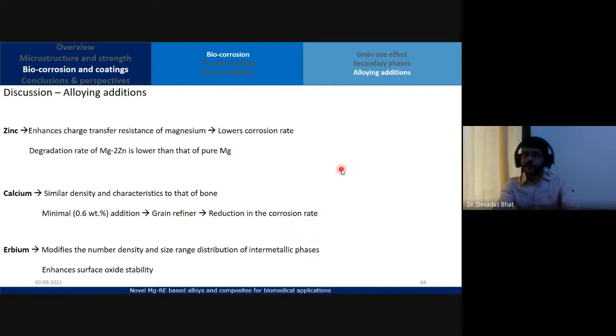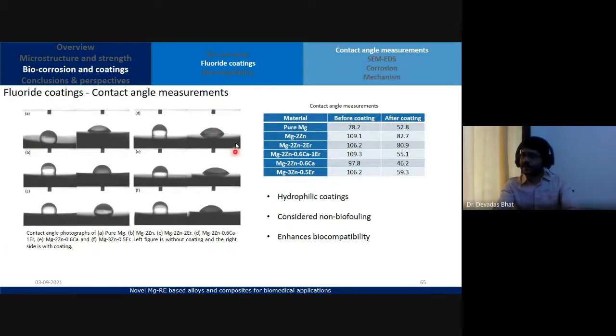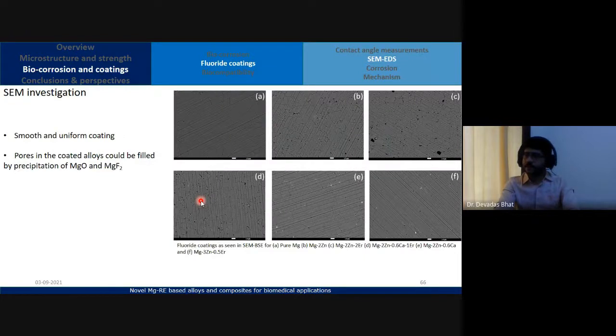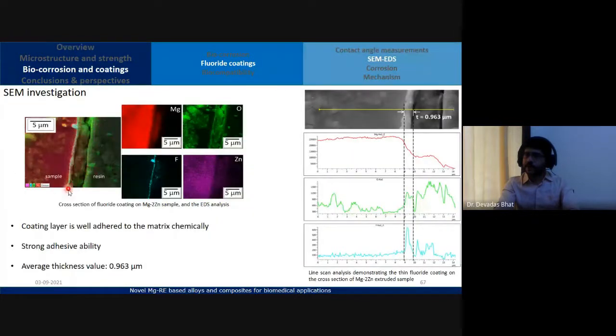Okay. All right, we did some coatings. These are certain results for coating. So these are the coated samples. We could see some hydrophilic coatings. That's the fluoride coatings, which improve the cell adhesion and proliferation. These are certain contact angle measurements. So this is a fluoride coating that we have done.